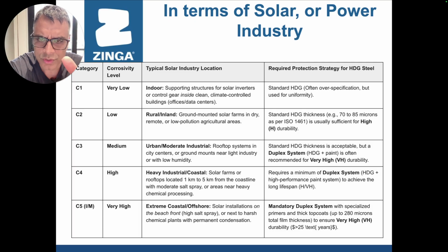C1 is indoor supporting structures for inverters or control gear inside clean, climate-controlled buildings. The usual suggestion is just a standard hot-dip galvanized structure, used for uniformity, and there is no issue at all. C2 also is very good. The corrosivity is low, so for ground-mounted solar farms in dry, remote, low-polluted agricultural areas, 70 to 80 microns of hot-dip galvanizing as per ISO 1461 is usually sufficient.